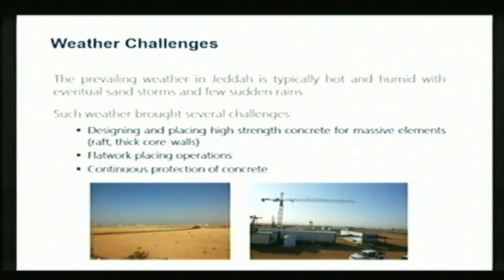You have to design and place high-strength concrete and high-performance concrete and mass elements, the raft, the thick core walls. You have to make sure that your finishing is adequate and curing is adequate for the flat work placing operations. And you have to always ensure there is continuous protection of concrete. Add to this issue the wind. The structural design of this project is based on wind. And not only is wind a critical factor in the structural design, it's also a critical factor in the construction, because you have to start dealing with wind when you're doing the core wall and building the slabs at the 60, 70 and 80 floor level. So you have to have wind breaks, you have to make sure that everything is protected and your own laborers and workers are protected.